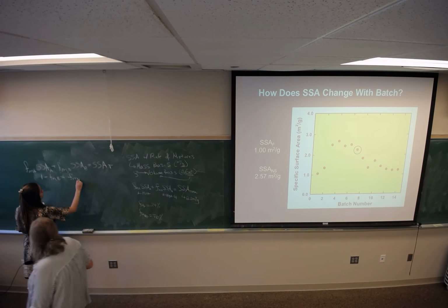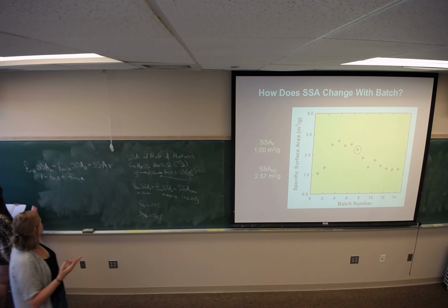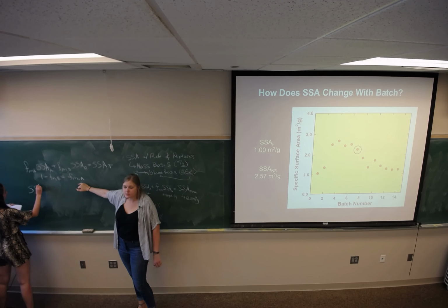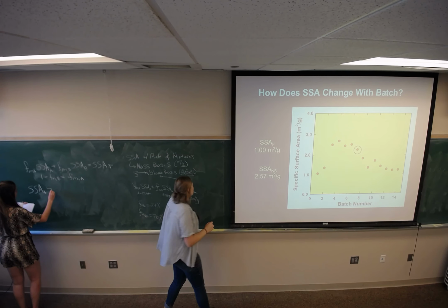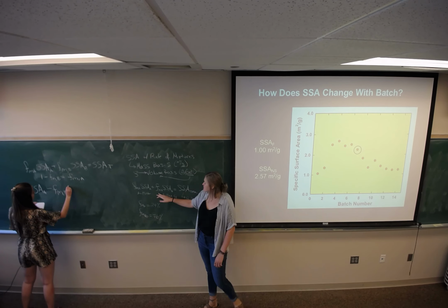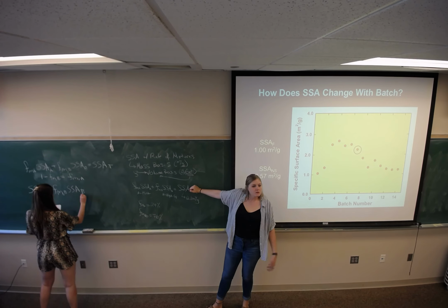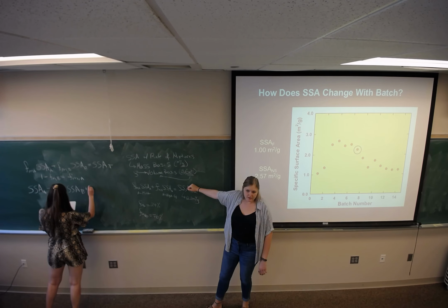So essentially what you're doing here is solving a system of two equations. You have your rule of mixtures equation here, and then your relationship between your total mass fractions. Can anyone explain why a problem comes up if we have more than 2 components with our rule of mixtures? Then you have 2 unknowns. Exactly, so we have 2 unknowns and only 2 equations, so we would need another equation in order to